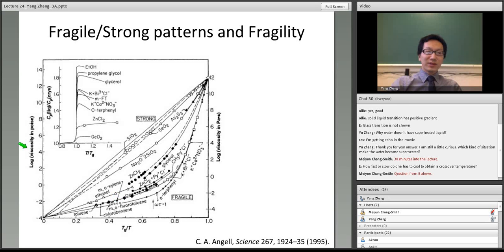If we plot the log of viscosity versus Tg over T, most of the materials fall into basically two categories. One category is the so-called strong. It's basically very close to a straight line. So for log of viscosity versus 1 over T, the slope would be basically the activation energy, as I mentioned in the previous figure on metastability. For strong materials, the activation energy is basically constant, or independent of temperature. For the other class of materials, most of them, the activation energy increases as the temperature approaches the glass transition temperature. And if we compare with this inset of specific heat, we can also see that these strong materials like germanium oxide have a very small change in the specific heat near the glass transition. But for all the other fragile materials, there's a huge specific heat change.